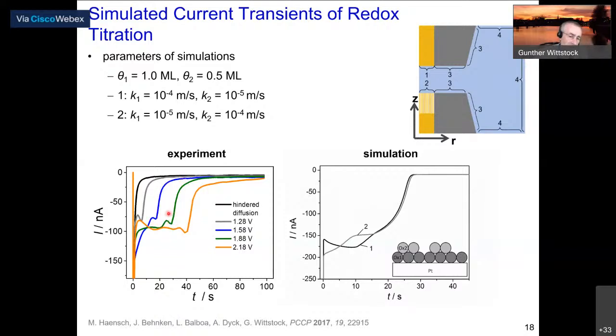So why is there a current rise just before the current is falling off? That is probably due to different kinetics of the reaction of the mediator with the oxide, which we can model. If we assume that we have two layers of oxides and we assume different rate constants for their reduction, then we can simulate curves like this. Then the rate constant of the first oxide is larger than that for the second one. And as we consume the second oxide layer, the first layer becomes more accessible, and the rate of that oxide reduction is increasing until everything is consumed, and then the current falls off.